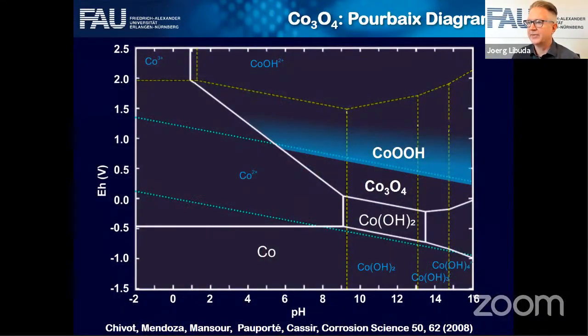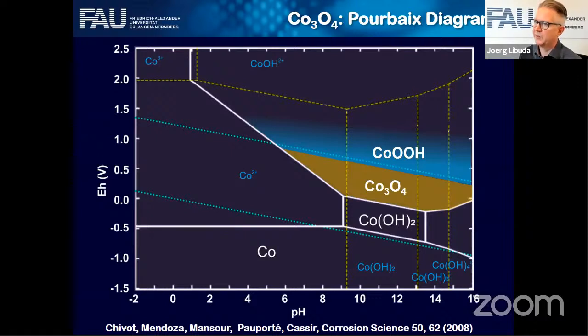Now, when you're bringing these systems into an electrochemical environment, a hostile environment in terms of surface science, you should think about what you're doing. So the first question should be, can I expect this material to be stable in the electrochemical environment? The electrochemist would look at a Pourbaix stability diagram and make sure that the experiment is run under conditions where you could expect thermodynamic stability. So this is this diagram, the stability of cobalt oxide as a function of the pH and the potential, and there's a certain region where cobalt oxide is stable, in the alkaline region.